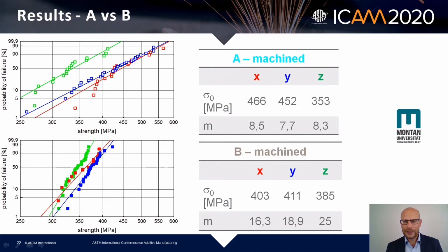Now we look at the mechanical properties, namely the strength. One thing which comes out first is that the A material, which actually has a lower density, has a higher strength compared to the B material. Sorry, what I forgot to mention is that both have been machined. As a standard testing method, they have been machined and chamfered and then tested. So the part which has a lower density has a higher strength, which is due to the smaller grain sizes.